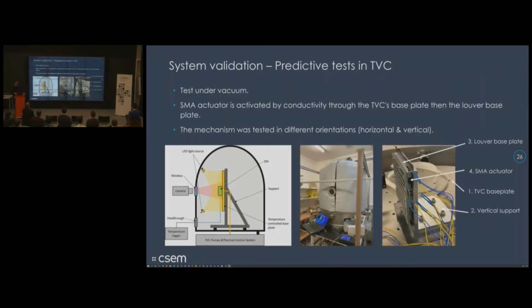The second part of our test campaign was this one. So here we placed the louver in a thermal vacuum chamber, and the objective was to test this louver under vacuum. In a few words, the base plate of the thermal vacuum chamber made some cycles from cold to hot temperature. And it means that the base plate of the louver and also the SMA actuator heated and cooled, and this temperature change created the opening and the closing motion of the louver.